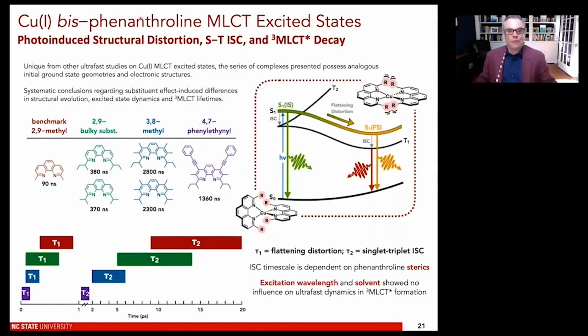Another part of my research program is really focused on how we design, through structural variation, long lifetime metal to ligand charge transfer copper(I) complexes. There's a lot of information on here, but the key thing is that you have to control the flattening distortion in order to control the lifetime. That requires a lot of ultrafast spectroscopy, which I won't get into. It also requires a lot of DFT calculations to figure out structure variation and what that's going to do to the flattening distortion. But without getting into all of those details, what you recognize is that the shorter you can make all of these time constants on ultrafast timescales, the longer the lifetime of the MLCT complex, and the better it's going to be for being susceptible to triplet-triplet annihilation processes.